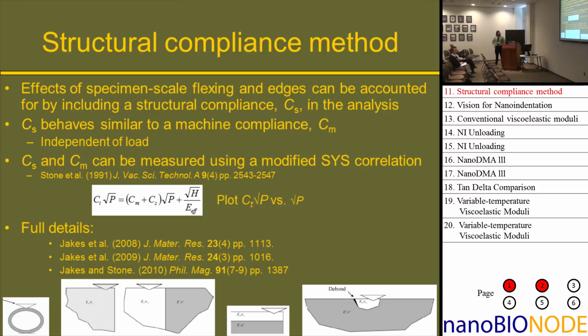Basically what we discovered is that both the effects of specimen scale flexing as well as edges can be accounted for by including a structural compliance in the analysis, and that the structural compliance behaves similar to the machine compliance. That is, it's independent of load. So you can use the standard equations that people use to account for machine compliance to also account for the structural compliance. And one such way is this modified SYS correlation.